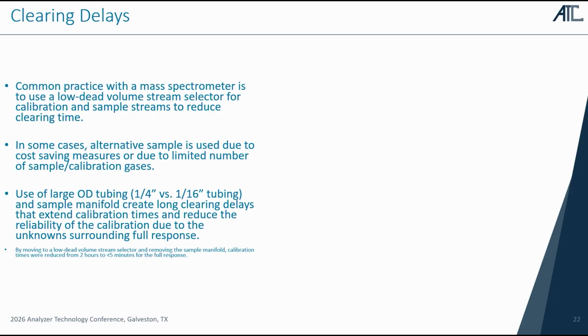And the reliability of the calibration was affected due to those responses and not having the full response factor at the time of calibration. We moved to a low dead volume stream selector and removed the sample manifold, so reducing calibration times from 2 hours to less than 45 minutes for a full analytical response.